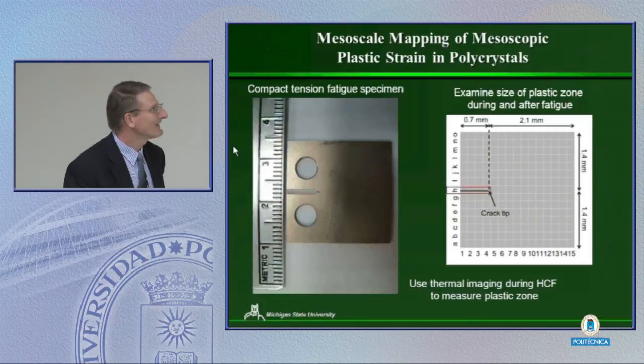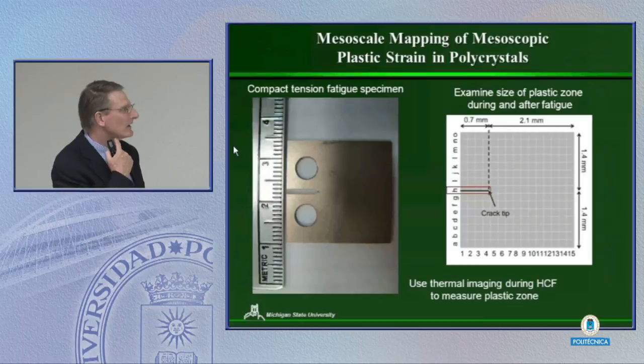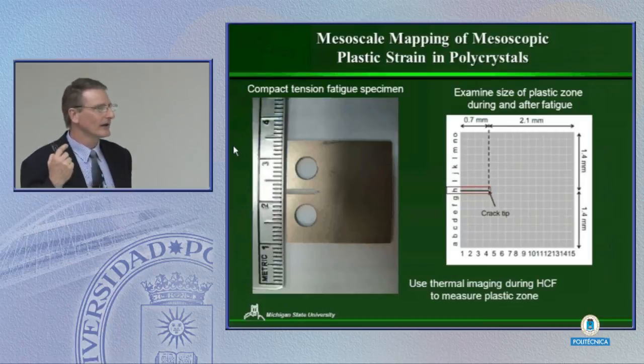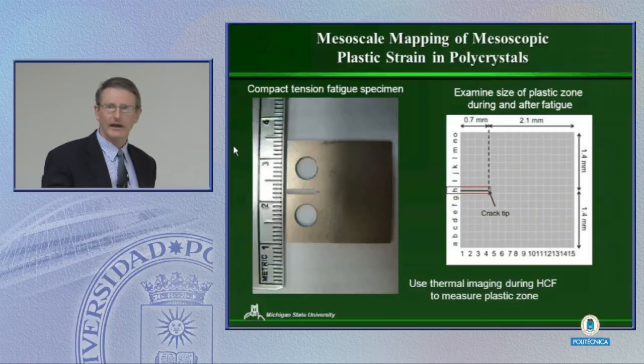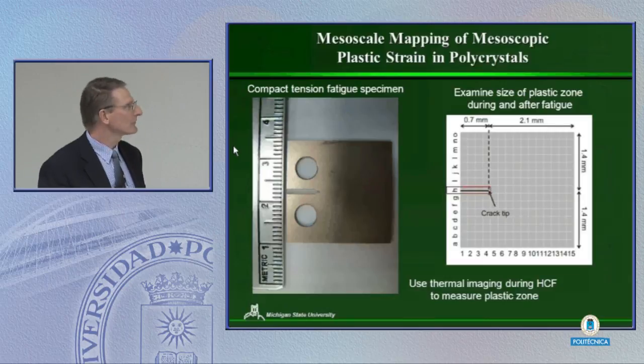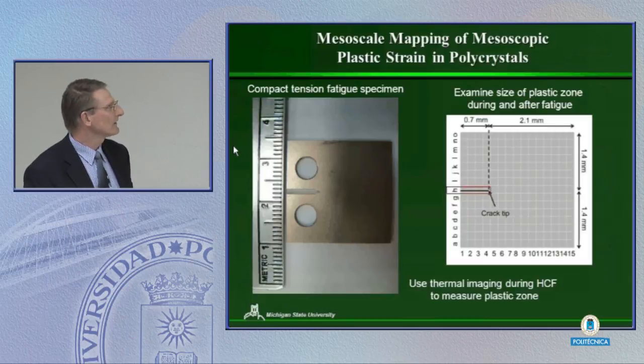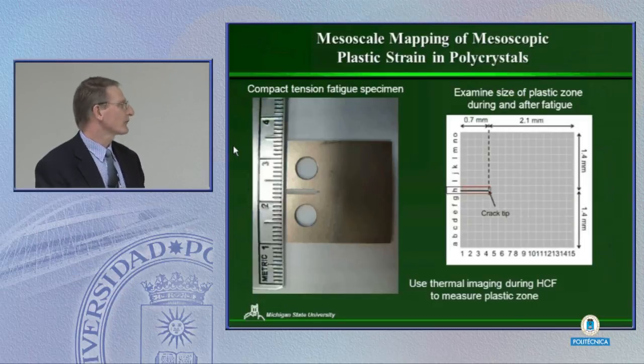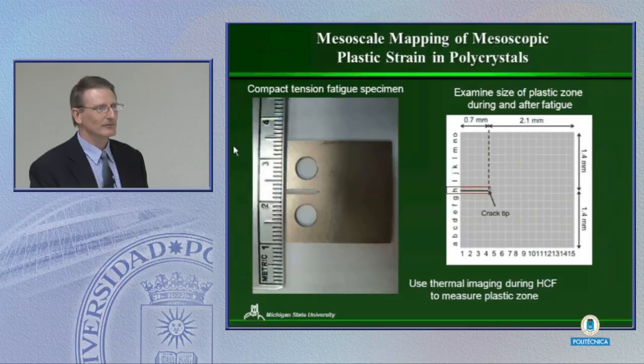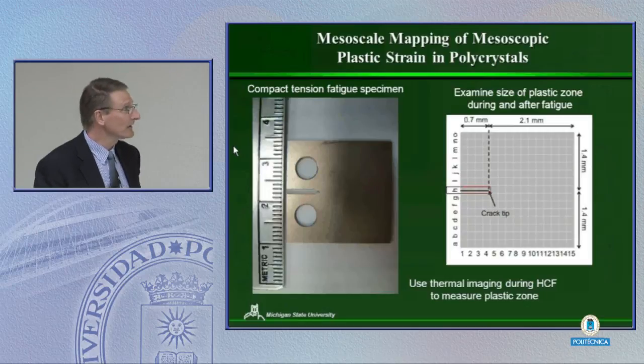Okay. And so I got working with Ian Patterson when he was at Michigan State and Rachel Tomlinson. She was on sabbatical from Sheffield. And they're doing fatigue tests in compact tension specimens. And they have crack tips, and I said, oh, I can look at crack tips. Well, it turned out that their crack tips had a lot of dislocations, okay? And we couldn't really image them specifically. But what we ended up doing is we said, okay, what happens if we look at this whole area out in front of the crack tip?